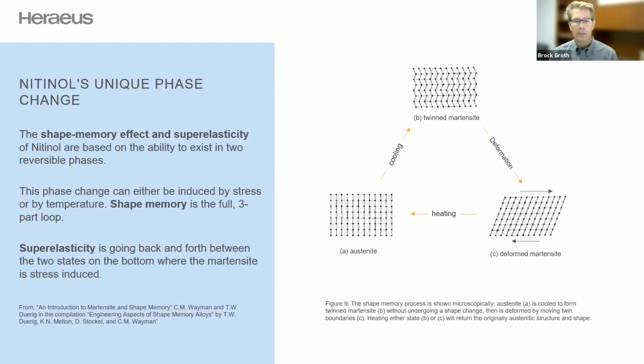And so the key to this superelasticity and shape memory is a phase transition. The most familiar phase transition that people know is water. Water goes through a phase transition from ice to liquid and liquid to steam. This is a phase transition. It just happens to be a solid to solid phase transition. And like ice to water and how it keeps your drink cold, there is a heat flow between these phase changes. Anyway, in the lower left, you've got this square outer form, you've got this square crystalline structure, and that is the high temperature or austenitic phase.